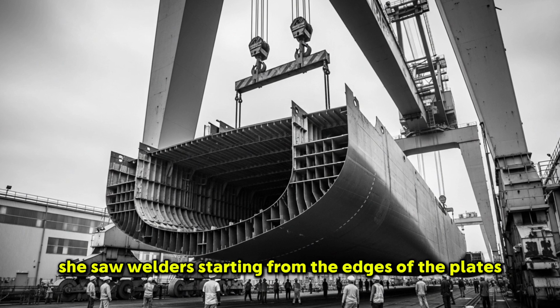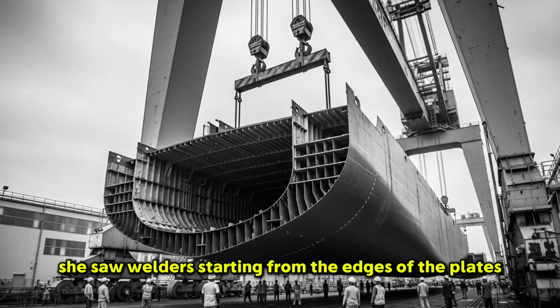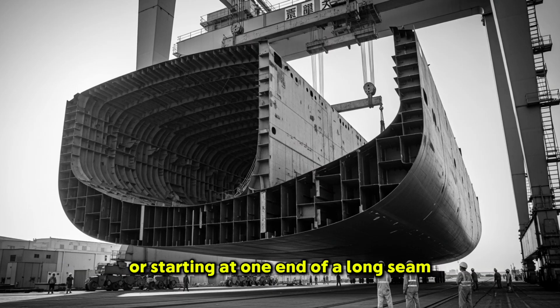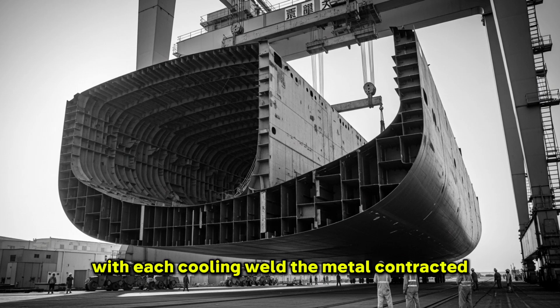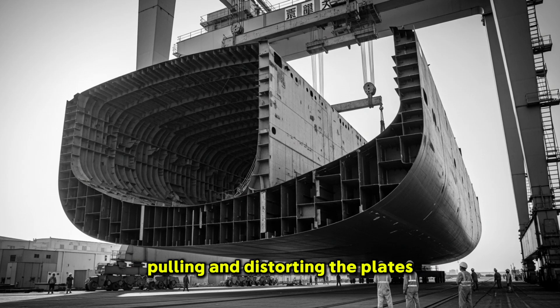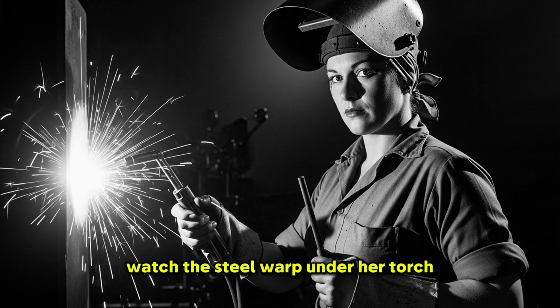She saw welders starting from the edges of the plates and working inward, or starting at one end of a long seam and proceeding straight to the other. With each cooling weld, the metal contracted, pulling and distorting the plates. She could see the stress building up, watch the steel warp under her torch.